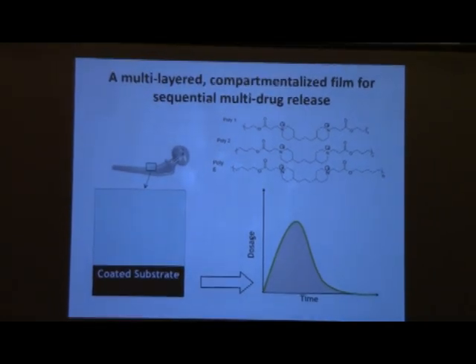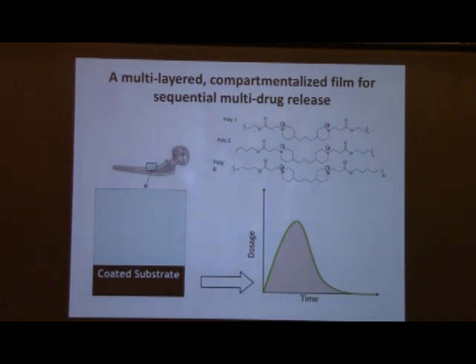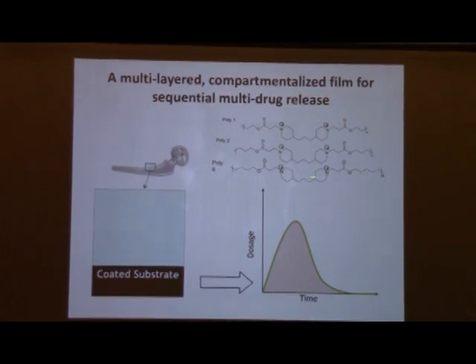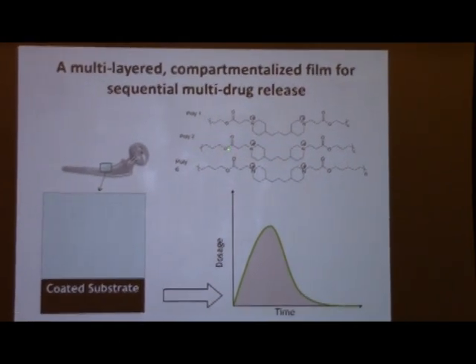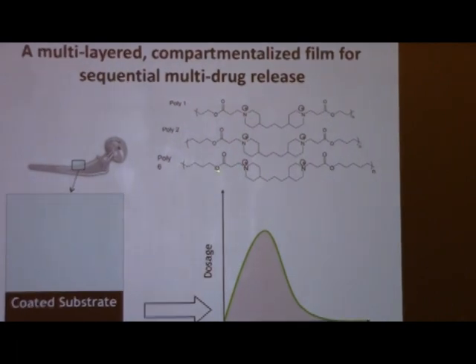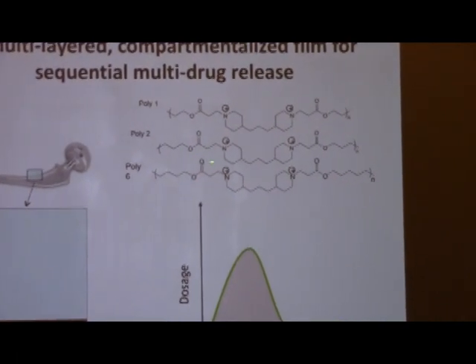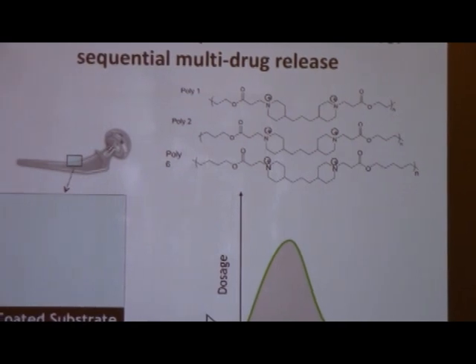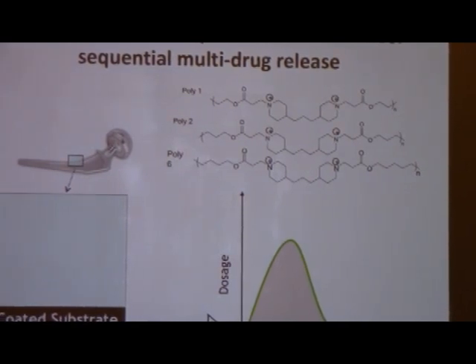On the other hand, with layer by layer, we have several advantages. First of all, there's the whole thermodynamic idea. Thermodynamics went against us when we were trying to make a blend, but if we're using charge as the regulator, then all we need is to alternate charge compensation rules. That means that if I take a degradable polymer that's water soluble and charged, like these here, here's a collection of positively charged polymers. They are also polyesters, but they have not only a degradable unit, but this charged unit, they can dissolve in water and be layered with a different drug molecule.